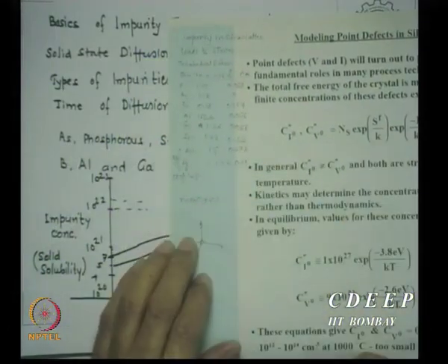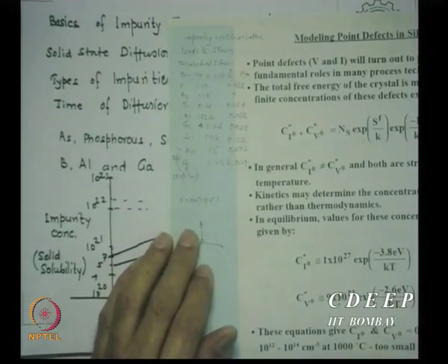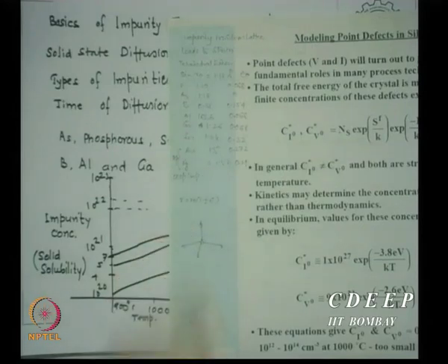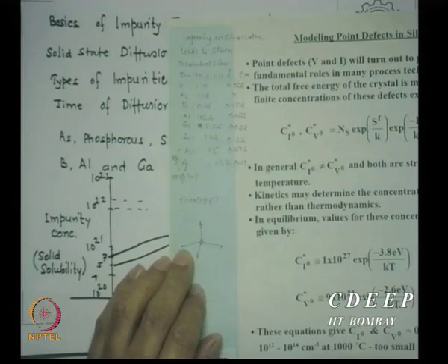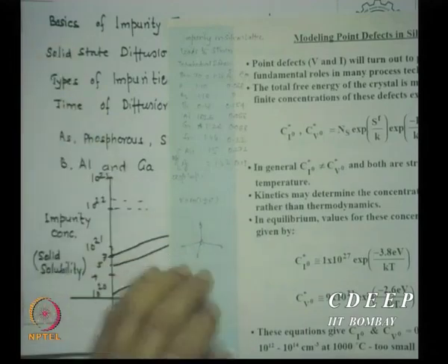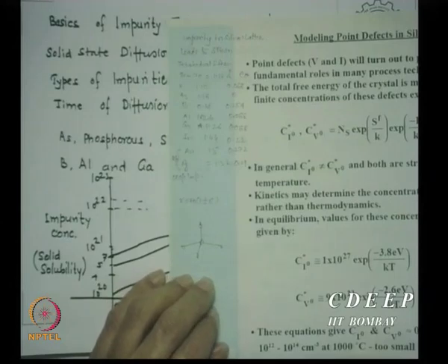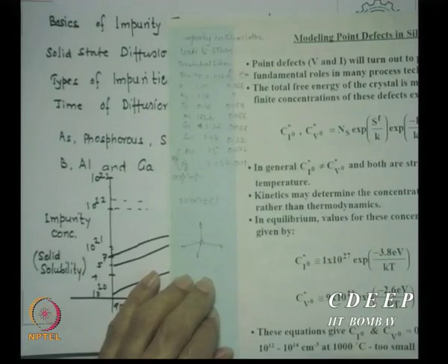So maybe I'll write down in that sheet, okay. I'll come back and maybe I'll read out this number so that you know. For silicon, R0, the tetrahedral radius, is 1.18 angstrom. Phosphorus, it is 1.10, okay. Arsenic, it is 1.18. Boron, it is 0.88. Please note down. Silicon 1.18, phosphorus 1.10, arsenic 1.18, boron 0.88, aluminium 1.26, gallium 1.26, indium 1.44, the largest atom around, okay.